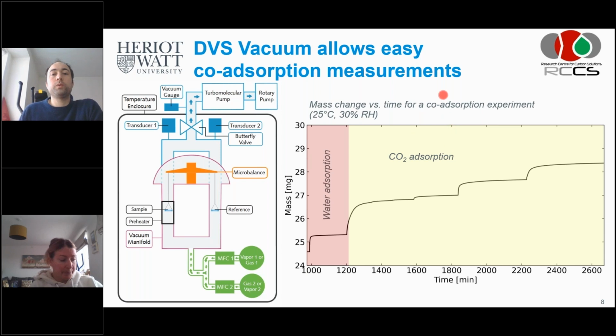So what we do is, of course, you first need to outgas completely, because water and CO2 adsorb so strongly to this material, any amine functionalized material, that you need to get rid of the water and CO2 as much as you can. So we need quite proper outgassing. I think we do it overnight at 100 degrees C, so for at least 8 hours.